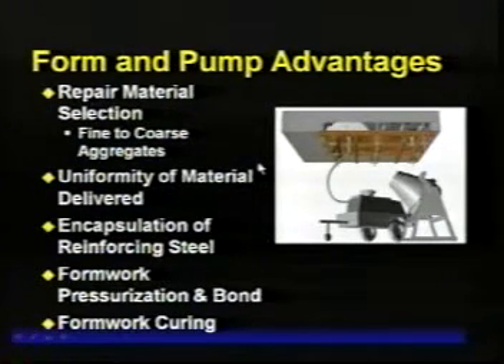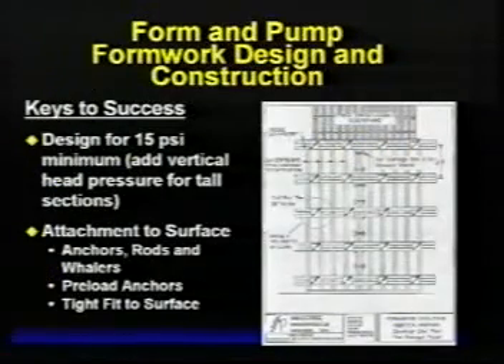As for the different materials used for this technique, basically anything that you can pump can be used. So it's not limited to fine aggregate. We've pumped jobs with 3/4 inch aggregate into these kinds of jobs. The formwork needs to be designed for the pressures, and generally what we have found is the minimum requirement is 15 psi, which doesn't sound like a lot of pressure, but it is a very stout form. That's about 2,250 pounds per square foot of load, as it has to resist the pressure of the pump line, and especially at the point when you cap it off.